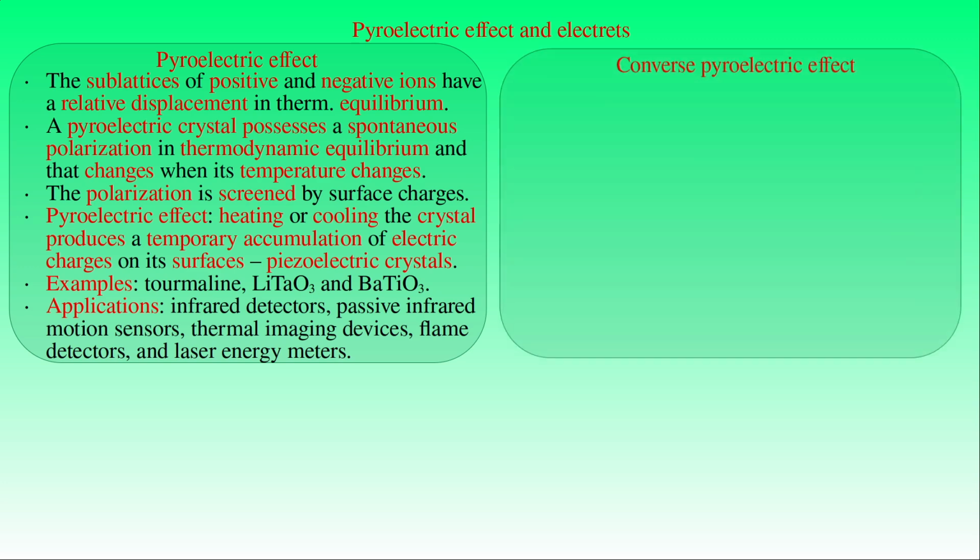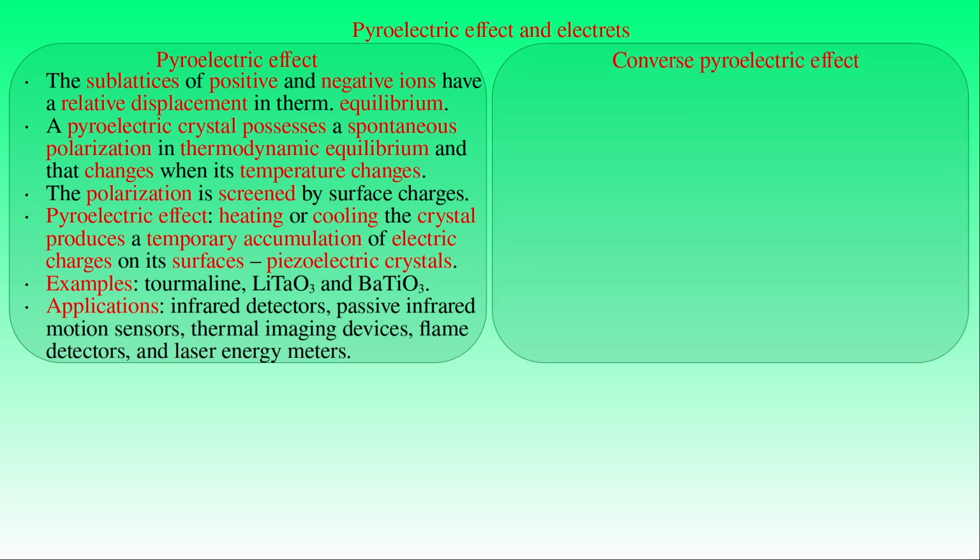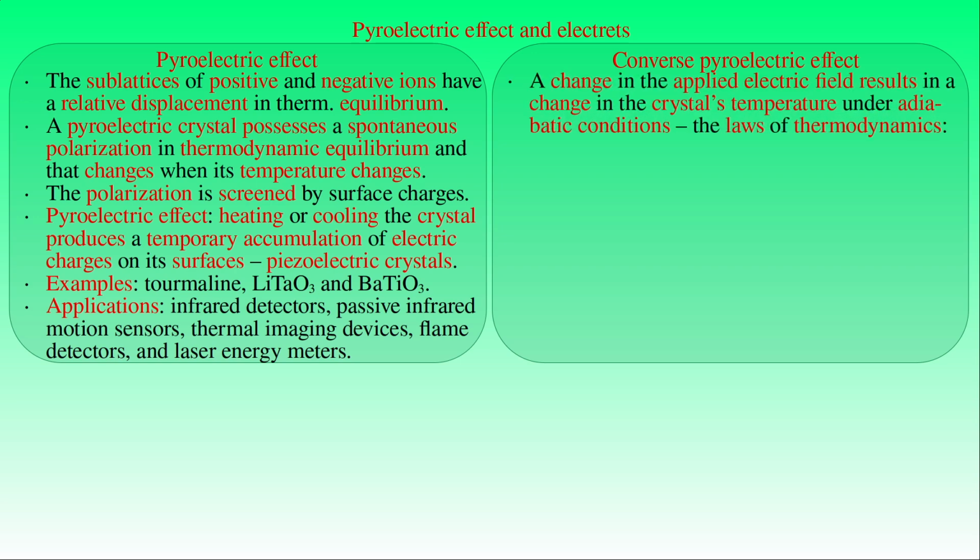Besides the direct pyroelectric effect, pyroelectric crystals also exhibit the converse pyroelectric effect, whereby a change in the applied electric field results in a change in the crystal's temperature under adiabatic conditions. It is a thermodynamic phenomenon where a material experiences a change in temperature or entropy in response to an applied electric field. The converse pyroelectric effect, also known as the electrocaloric effect, is the exact thermodynamic reverse of the pyroelectric effect, and it can be shown that this effect is a necessary consequence of the direct pyroelectric effect and the laws of thermodynamics.